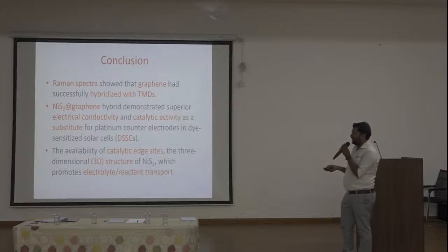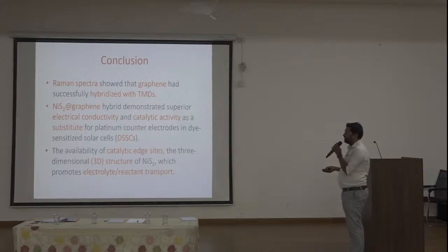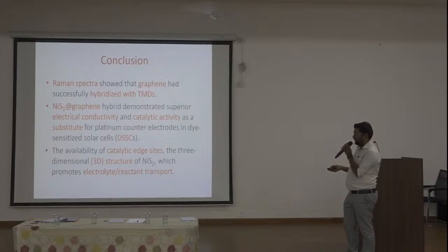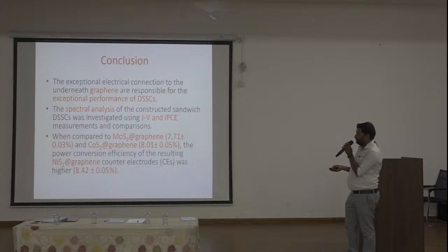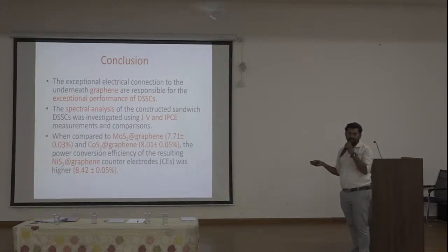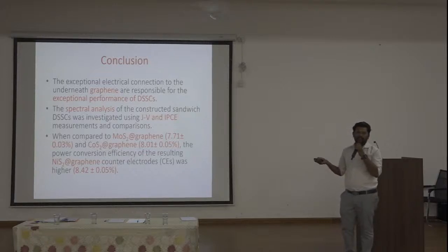So among these 3 different types of material, NiS2 with graphene has good electrical conductivity and catalytic activity, which makes it a substitute for the platinum counter electrode, and it has good catalytic edge sites, a 3D structure, and electrolyte/reactant transport. So exceptional JV performance, current density value and power conversion efficiency. Overall, the best performance is from nickel disulfide, at 8.42 plus or minus 0.05. So this is suitable for the counter electrode. Nickel disulfide with graphene is the suitable material for platinum-free DSCs.